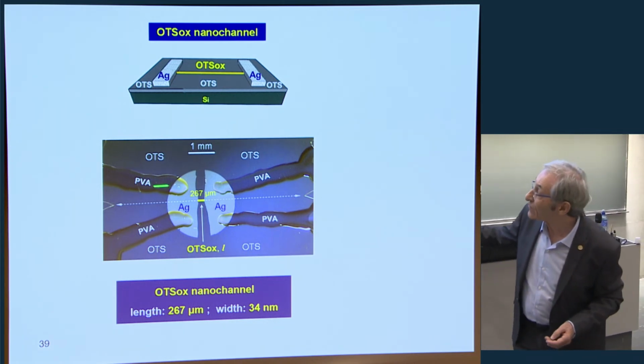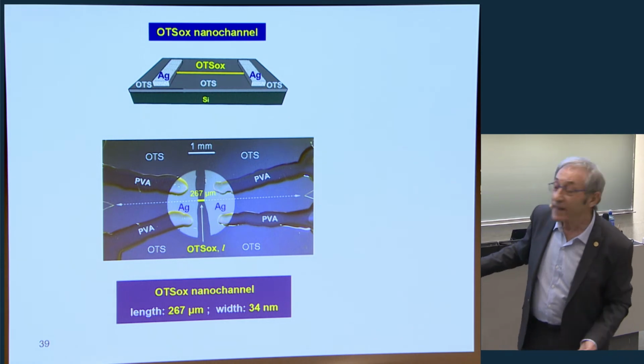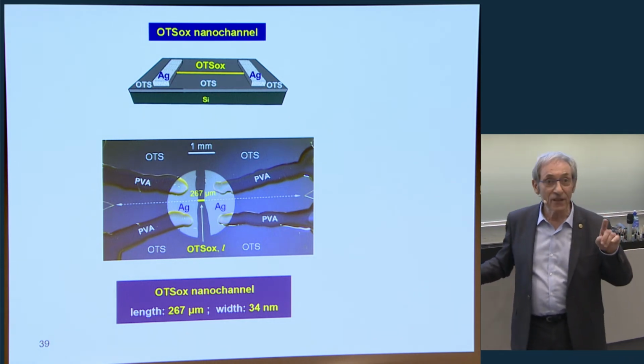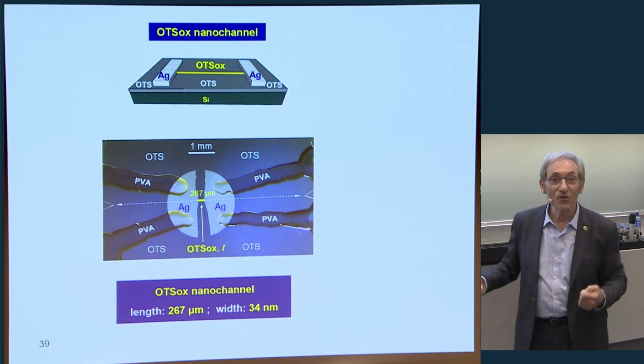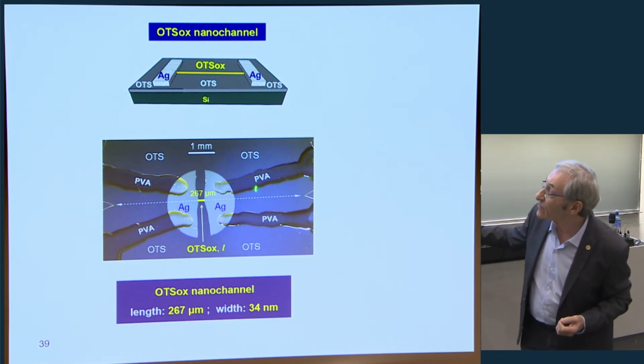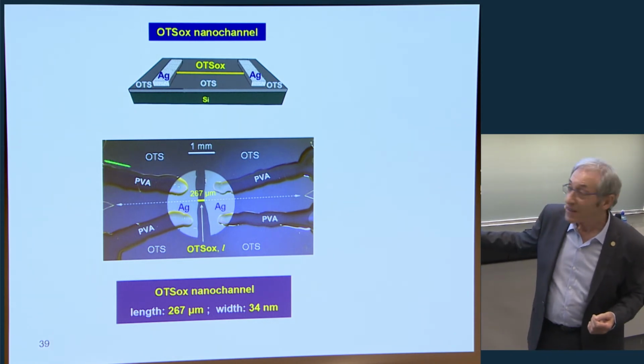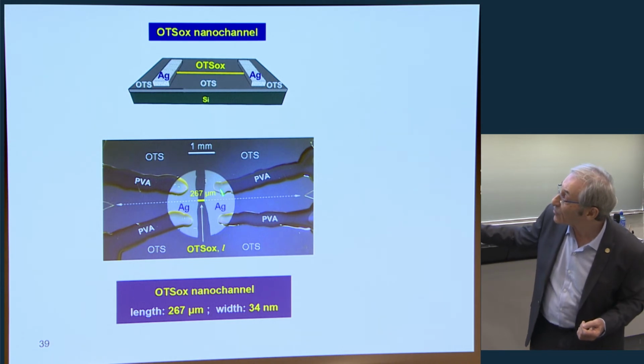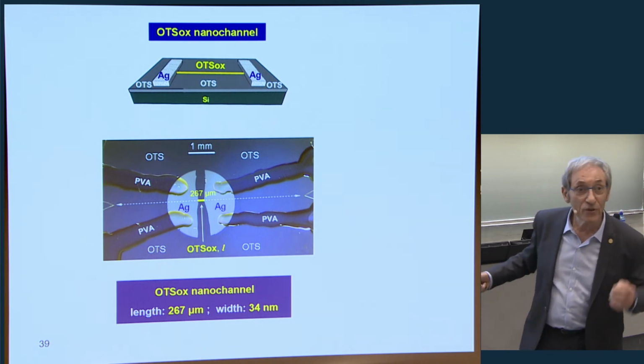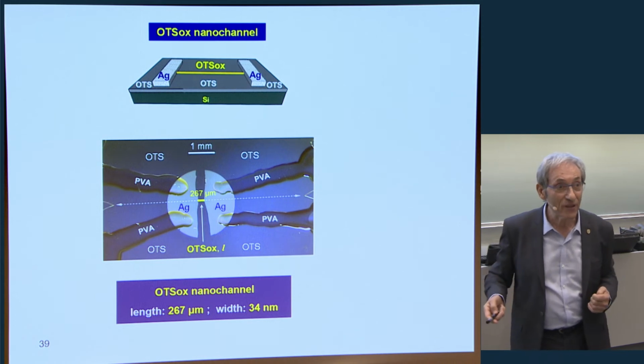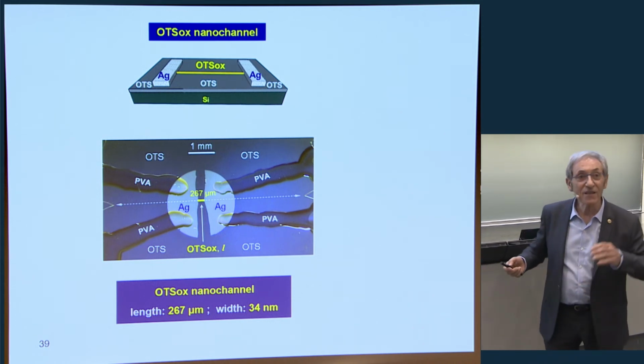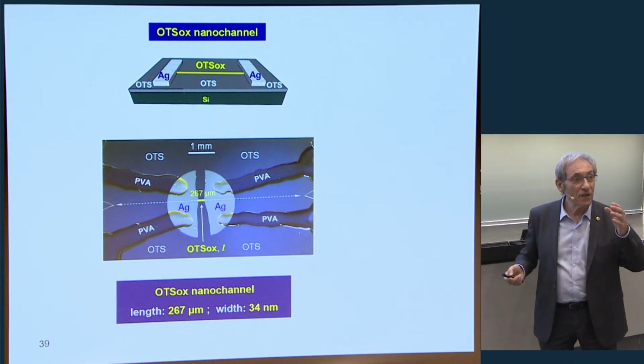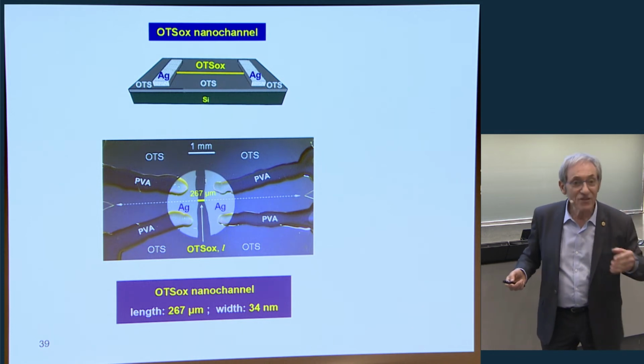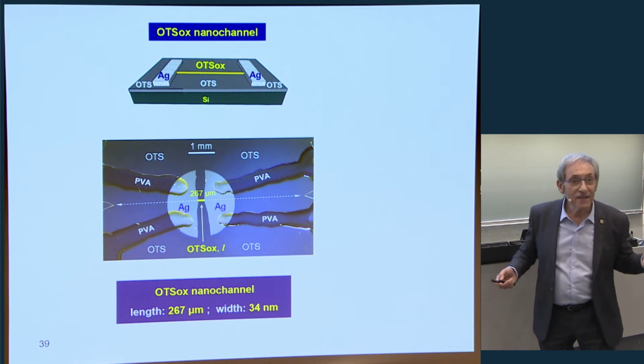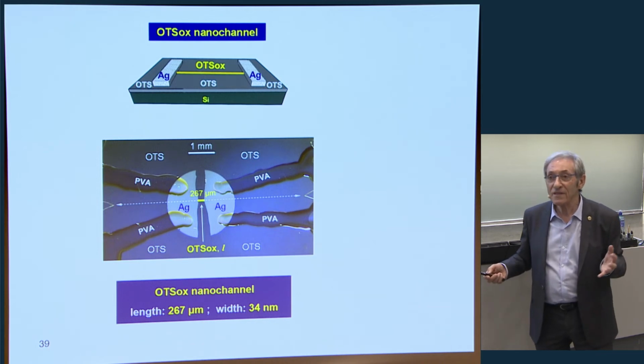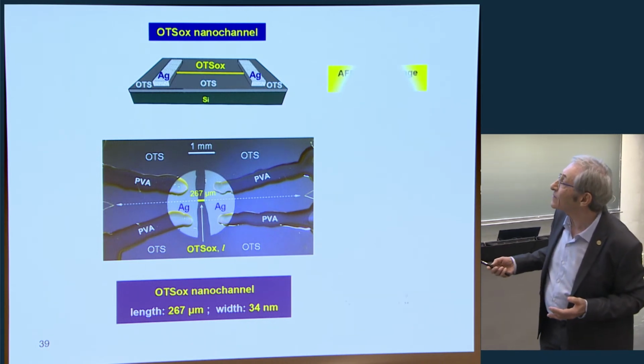And then we evaporate 2 silver electrodes. And in order to make soft electrical contacts, so we don't go through the monolayer, we use polyvinyl pads, and the electrodes are evaporated on top. So now when you touch here with the probe, it doesn't go into the monolayer. This is also important. There are small details that, if they are not processed well, you don't get anything. So, you know, the secret is in the small details.